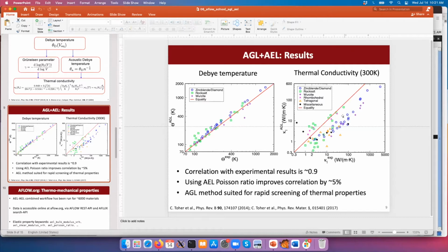So usually, what you're arguing is true if you're trying to calculate the different scattering mechanisms. You will tend to have a thermal conductivity that's too high because you haven't included higher order phonon scattering mechanisms. In this case, we're not directly trying to calculate the individual scattering events. At this level, you're trying to just estimate what the scattering events would be from the anharmonicity of the energy volume curve. So it integrates all the scattering mechanisms, and it actually tends to result in an overestimate.